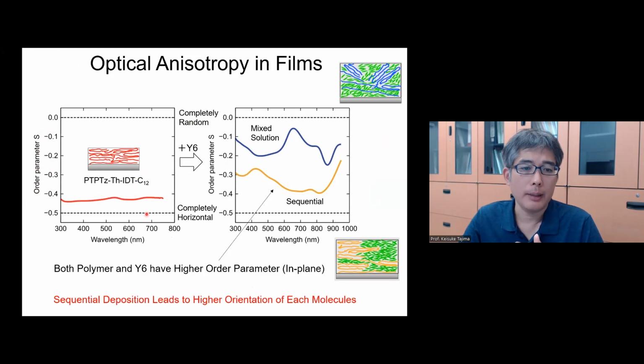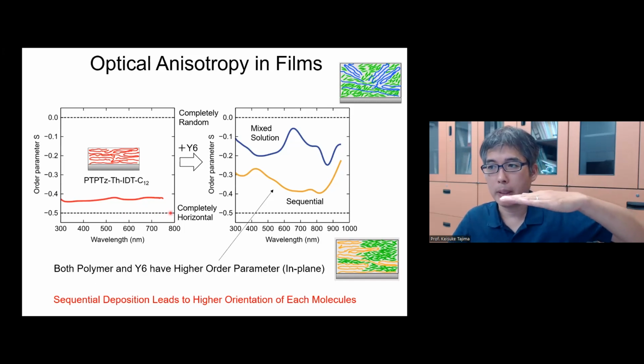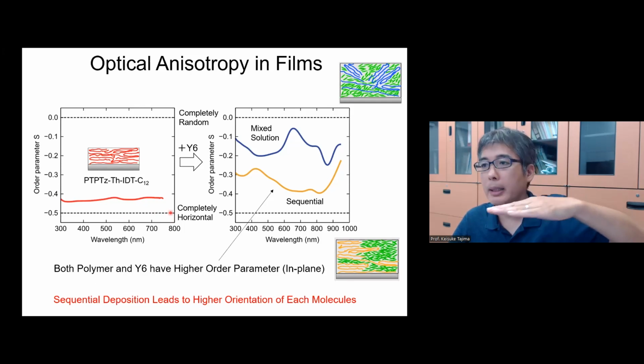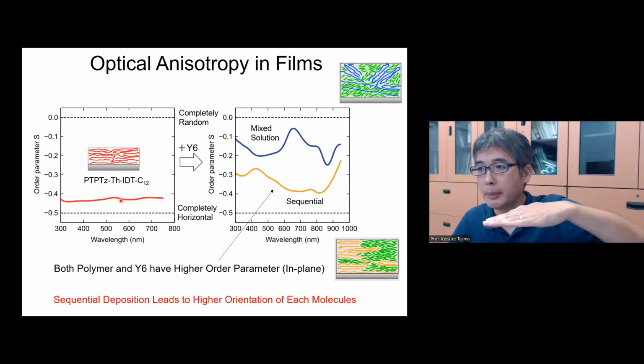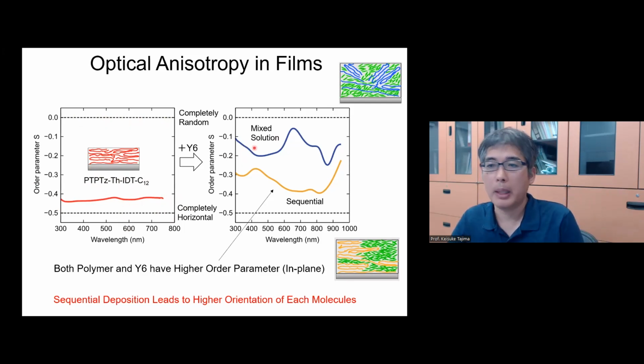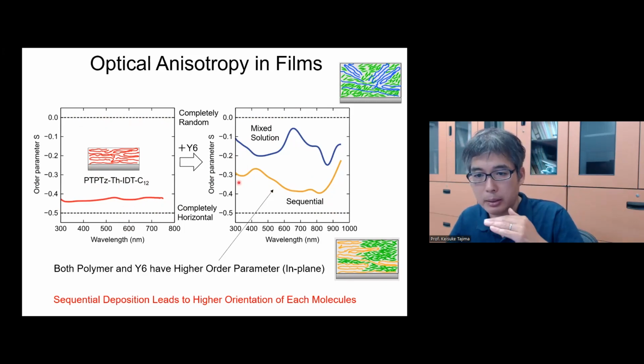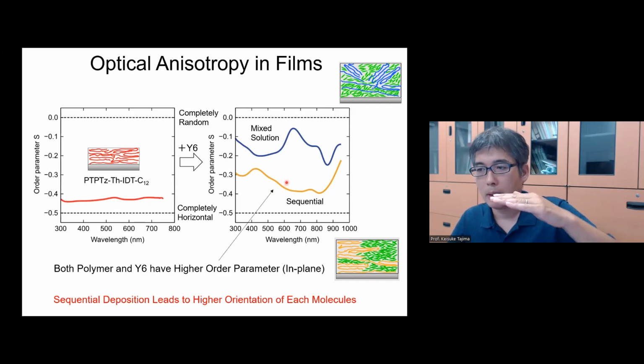Here I show the graph with the order parameter on the y-axis. That means that negative 0.5 means completely face-on, or more like in-plane absorption, and 0 is random. Right? So this zigzag shaped polymer has a very strong orientation in the in-plane direction. That is good, and we had already observed that. But when you compare the bulk heterojunction film prepared by the mixed solution or sequential deposition, there is a large difference in the orientation degree. So sequential deposition gives you a much higher order in terms of the face-on orientation, right? So this has a larger absorption in the in-plane compared to the mixed solution bulk heterojunction film.